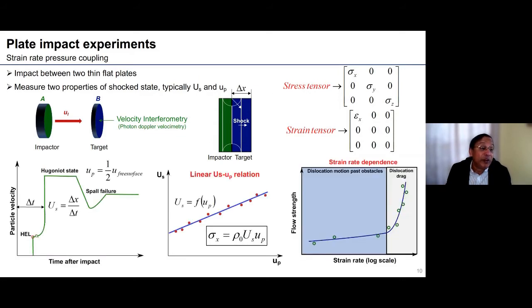So this is just showing what I just said in words. If you look at the profile of the free surface particle velocity measured using a PDV or VISAR, you observe an elastic jump, the elastic precursor, which is the Hugoniot elastic limit. Then you have the elastic-plastic shock wave, and then you reach the Hugoniot state where you approach the hydrostatic state of stress. And obviously then there is the release, and if the conditions are right, one can create spall failure and so on. And the particle velocity is one half the free surface velocity, which you can obtain.